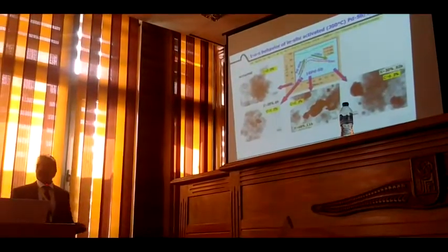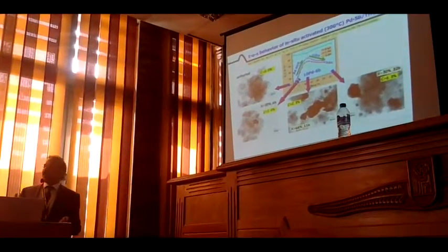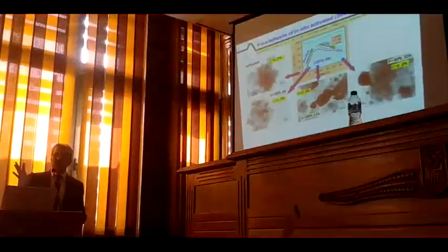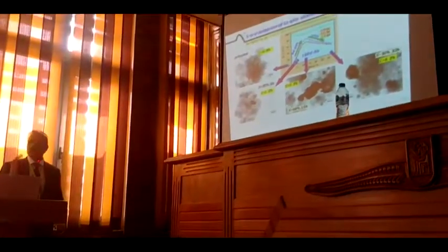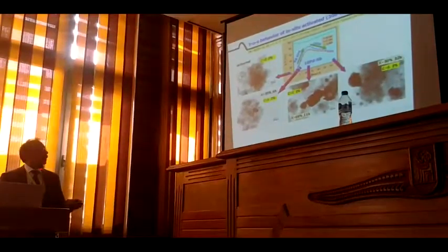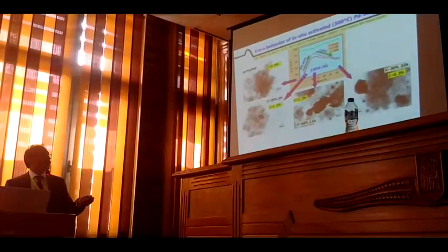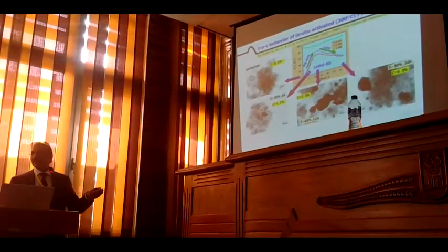Even though there is 2% coke, the catalyst is still able to show the maximum activity. This means the 2% coke is tolerable coke. It is not able to block all your palladium sites. It can sustain 2% coke. But if you go further, if you have 4 or 6% coke, the catalyst is undergoing deactivation.